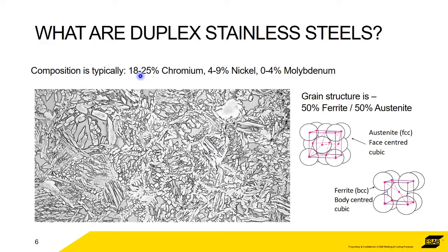It doesn't necessarily mean that all the families of duplex have to have exactly the same amount of chromium, the same amount of nickel. You can see typically chromium is between 18 and 25%, nickel between 4 and 9, and then anything up to 4% of molybdenum.